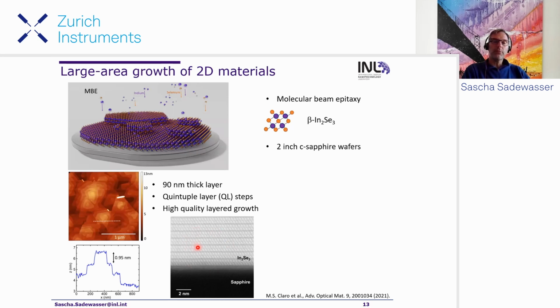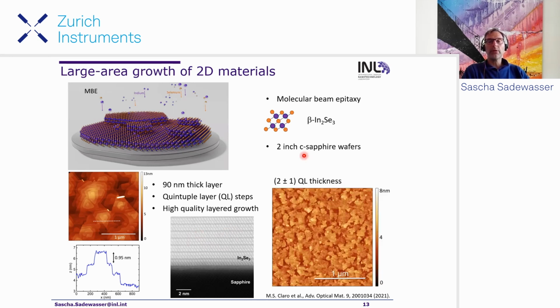We also did TEM to confirm that we have actually, over a very large area, almost perfect crystal growth with very little defects in the material. We can control the growth. So this was a very thick layer here, 90 nanometers, but we can control the growth to about 2 ± 1 quintuple layers, which is shown here, very flat surfaces.